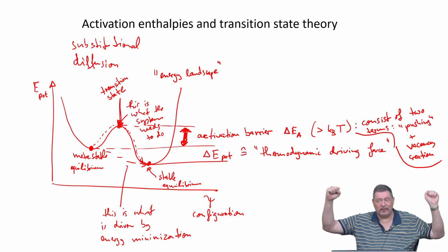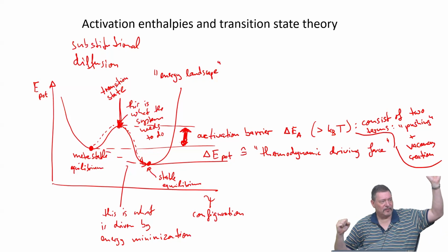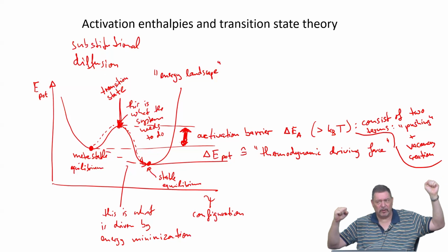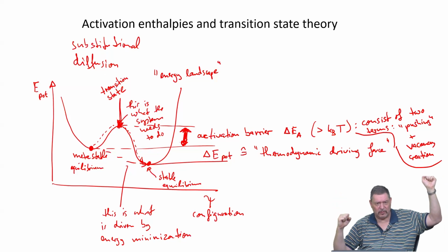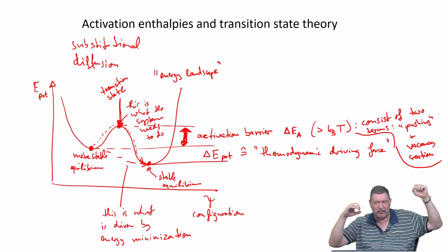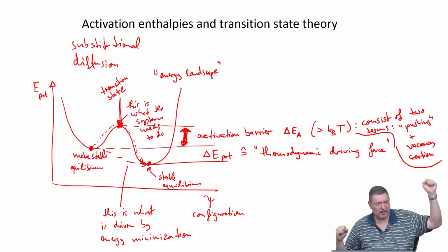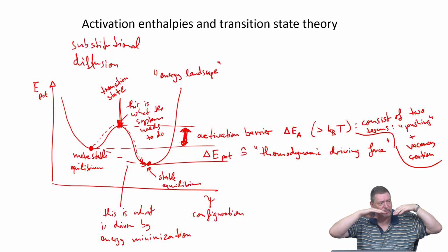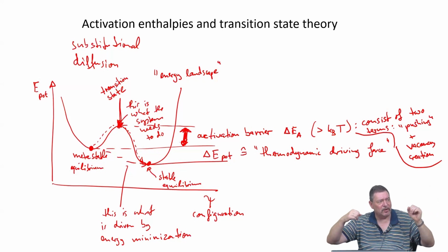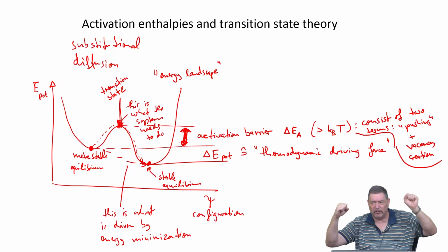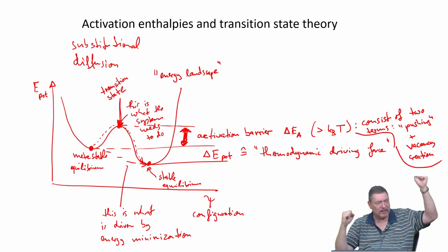You basically tilt it. Any gradient of a field will basically tilt your energy landscape. So it means also that maxima can become saddle points. So it means that the diffusion process will be eased because it's more going downhill if you apply, in this case, the electrical potential gradient to the system.